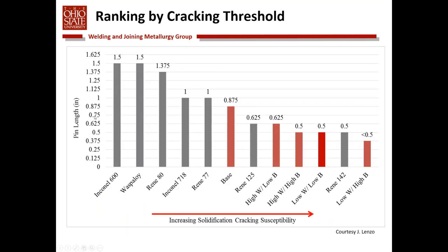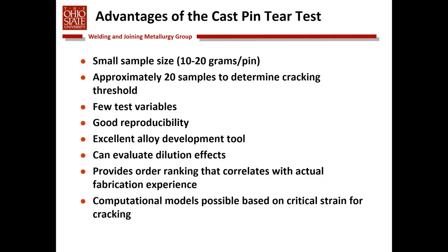So we can basically rank this data by cracking threshold. So what is the critical pin length at which we first get cracking? And you'll see a cascading distribution of behavior here, again, with the materials on the far left being the most resistant and the materials on the right being the most susceptible. So again, it's turned out to be a pretty reliable test with respect to predicting solidification cracking.